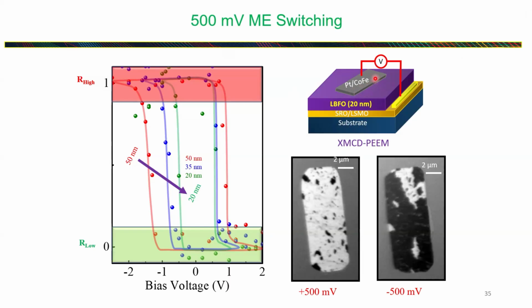Okay, we put this on the top of that, and we apply an electric field. What we see is that when you apply a positive 500 millivolt, most of the domains are white. And when you apply a negative 500 millivolt, you can go from white to black. So basically, with just the electric field, you can manipulate these magnetizations from one state to the other without any magnetic field.